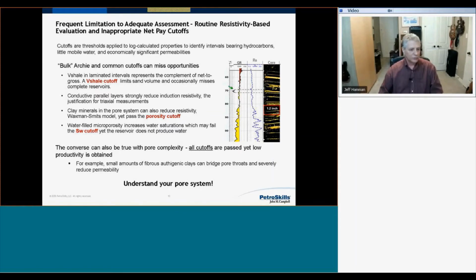A V shale cutoff, which is common, in a laminated interval actually represents the complement of net to gross. So 1 minus V shale really is the sand volume, and if we have a shale cutoff of, for example, 50%, then we will limit our sand volume and occasionally miss complete reservoirs. The same is also true that we will have shales in what we're calling all net, but the point we really want to make here is that we are going to underestimate the length of our reservoir because of the cutoffs. We'll lose some net thickness, and occasionally, as in this core UV (ultraviolet light) photograph, where the fluorescence represents oil, we would have zero net at a 50% V shale cutoff.